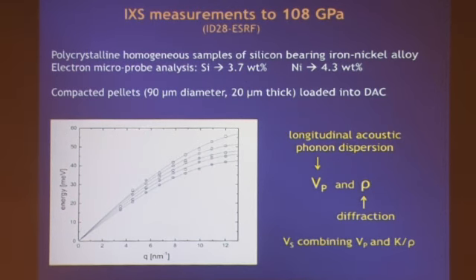So we look at a polycrystalline homogeneous sample of a silicon-bearing iron-nickel alloy prepared by pressure, temperature, interdiffusion in a piston cylinder press, and the chemical composition was determined by electron microprobe analysis. And the data I'm going to show you are for a sample containing 3.7 weight% of silicon and 4.3 weight% of nickel. A compacted pellet of suitable dimension has been loaded into a diamond anvil cell, and examples of the aggregate phonon dispersion collected for increasing density are reported here. We constrain the aggregate dispersion in the first Brillouin zone by 8 to 9 Q points, and we derive from a sine fit to the data VP with typical determination around 2%.